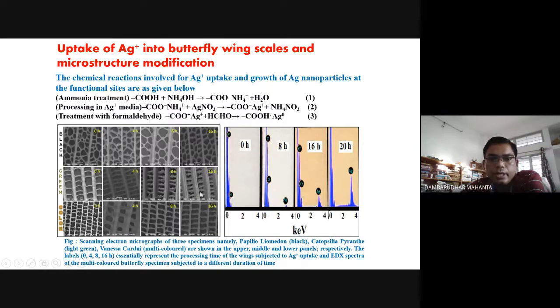So silver is staying somewhere, and we cannot measure the presence of silver everywhere. What we have considered is the central point of each ridge, where we measured the percentage of silver. And this is the EDX spectra on the right hand side. You could see at 0 hours you do not have any silver, and slowly silver is coming and the amount of silver is increasing, and after 20 hours of soaking we could see that silver is now prominent. The system is still intact after 16 or 20 hours. But of course up to 2 days one cannot go, it's not recommended, because these are very delicate, and sample handling is the most difficult part.